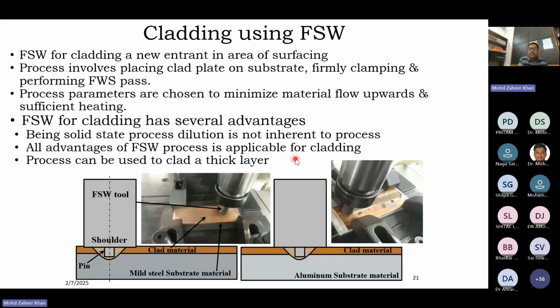So to test our idea, this type of friction stir cladding experiment was carried out. In this method, we took two different substrates. One was an aluminum substrate, another was a mild steel substrate. In both cases, we tried to clad a layer of copper on the substrate. Now I must again mention that copper as a material has a problem of compatibility with both mild steel and aluminum.